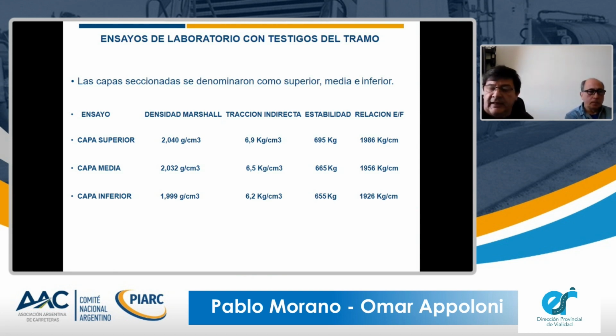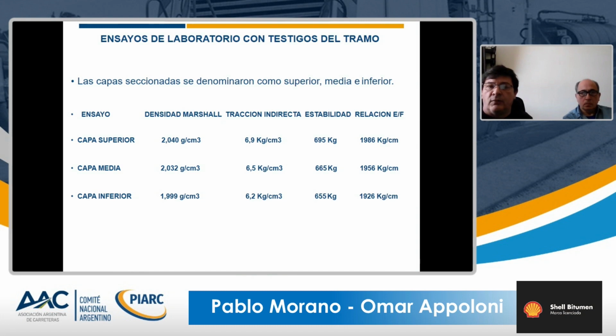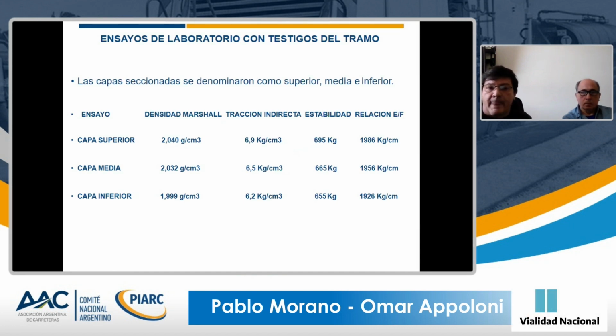We cut these cores in 3 sections, and compacting was in one of the stages of the total thickness to check whether there was good compaction and behavior in the whole thickness. As I said, we studied the top, medium, and bottom sections.